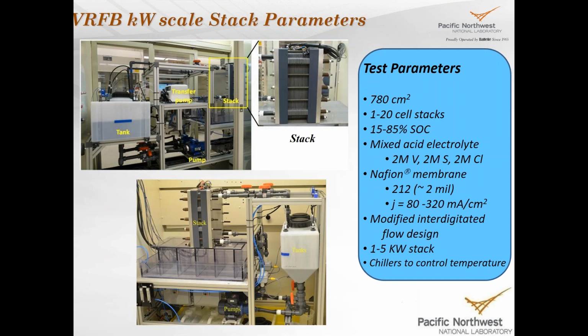So this is our current 5 kilowatt stack system. It has around 800 centimeter square of active materials, a 20 cell stack. We're working on the SOC range from 15 to 85. With our mixed vanadium electrolyte, the current density is up to 320 milliampere per centimeter square, a four-fold increase from our previous systems.